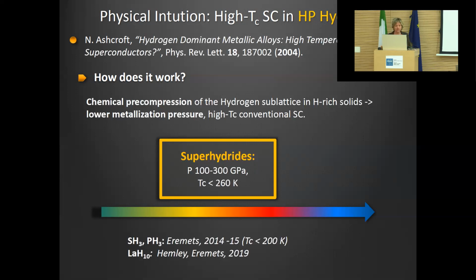And we now know that this idea was actually good and it actually worked. It took around 10 years for the group of Eremets to measure for the first time a high TC, meaning around 200 K, in SH3 at 200 GPa, and it took only 5 years to reach what is now the record, around 260 K, in another high-pressure hydride, which is lanthanum H10.